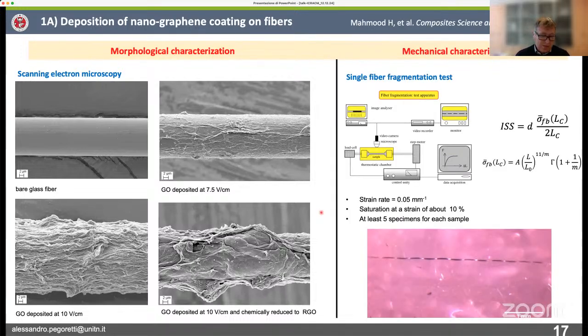How did we measure the effect on the adhesion? We used the single fiber fragmentation test. Here you can see the configuration. Basically, we embedded a single fiber in a coupon of matrix, and then we loaded this coupon, and with a microscope, we observed the generation of fragments, which are quite evident in this picture. And at the end, when the saturation of the process is reached, you can reach a length, which is called saturation length, which is proportional to the critical length. This critical length allows us to determine the interfacial shear strength. This is the typical way these data are collected and analyzed in the literature.